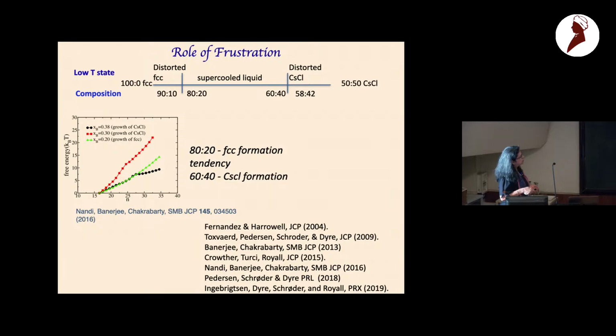We could show that here is the growth of FCC structure. There is this barrier for FCC formation. We could never find a barrier for CsCl formation even in biased Monte Carlo simulation. If you put a CsCl crystal seed there, everything around it would grow as only FCC and not a CsCl structure. So if I had to see a barrier, that barrier would be probably somewhere sitting there, or an infinite barrier.